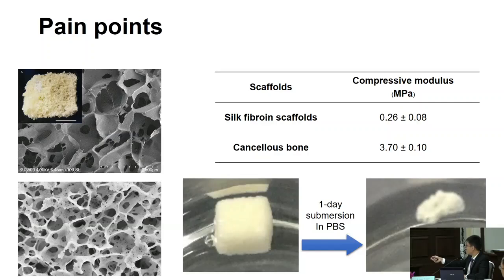The lower picture here is the cross-section of the bone under SEM as well. So you could see that these two structures are very similar, and we hope that the bone scaffold from Thai silk fibroin would behave very similarly to the actual bone. But the problem is that when we compare the mechanical property of silk fibroin scaffolds to the cancellous bone, you could see that the compressive modulus of the cancellous bone is a lot higher. It's more than 10 times higher than the silk fibroin scaffold.